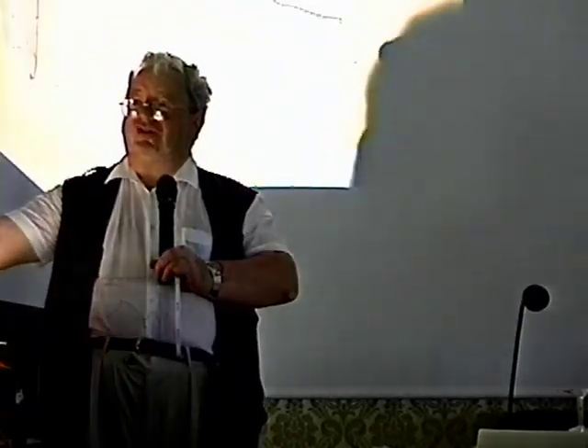And what do we get? Sorry, just a minute, because there is some disorder in my transparencies. We have the following graph. First graph, the plate. The red line is the density of current, and the blue line is the ratio R over R naught, which, as you say very well, is the indication of the loading. And we can see that when we apply current, the system is loaded, and when we remove the current, the system discharges. What does that mean?